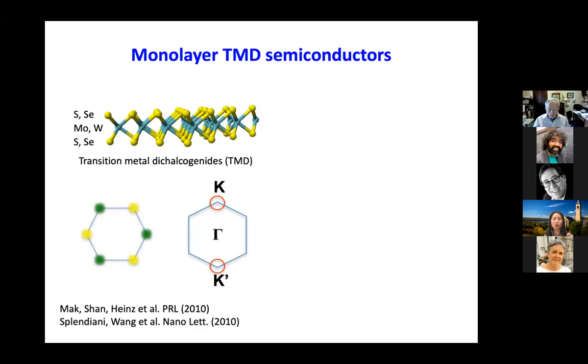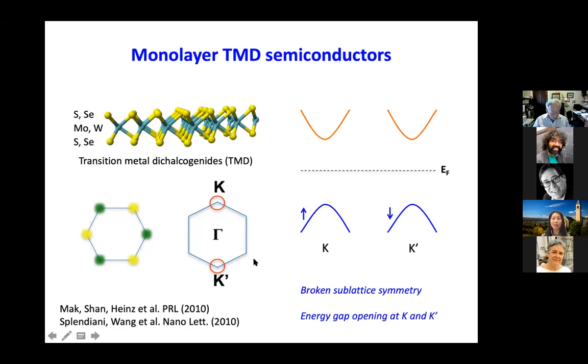So if you look down from the top, it just looks like graphene. You have metal on the A side, and you have the selenium or sulfur on the other lattice site. And the electronic band is very similar at low energy. So sort of like graphene, but now we have a band gap. We have a heavy metal here, so the spin orbit interaction is strong, and that will lift the spin degeneracy of each band. So those bands are spin polarized.